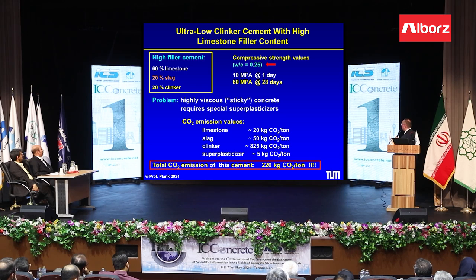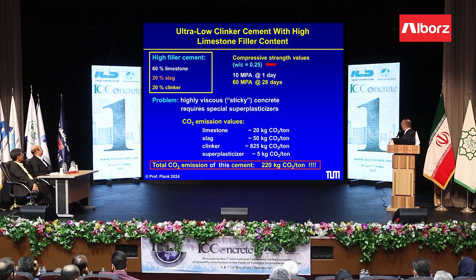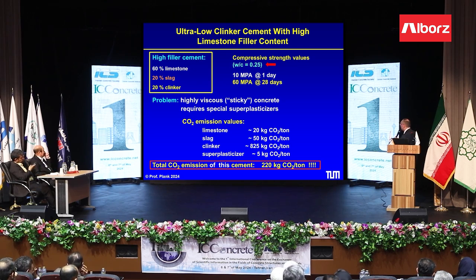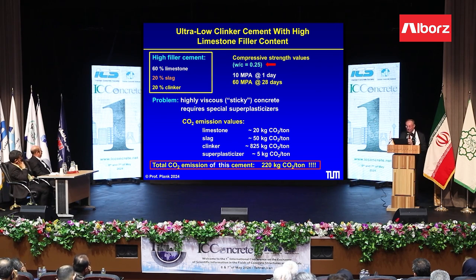Another example, this is an ultra-low clinker cement with high limestone filler content, and you can see 20% clinker, 20% slag, and a lot of limestone. And if you go to a very low water to cement ratio, you still can get 10 megapascal after 1 day and 60 after 28 days. So with this cement, you have a cement with a very low carbon dioxide emission. We call it a climate positive cement, which means it reduces the CO2 emission more than what we need, and still we can get very attractive strength data. But the key is the superplasticizer. If you work at this water to cement ratio, you need a very powerful PCE.